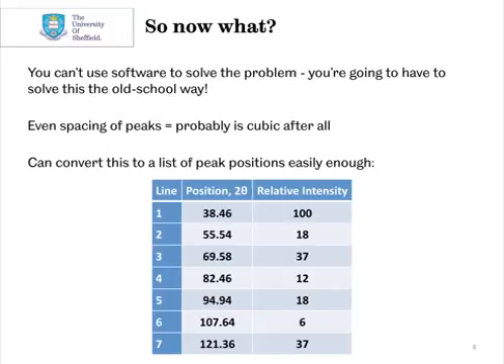From the diffraction pattern, we can see that the peaks are spaced fairly evenly. This indicates that the sample probably does have cubic symmetry after all. So we can create a peak list quite easily. As you can see here in the table, we've got our 7 peaks from the diffraction profile, and we've listed the peak position in theta and the relative intensity. What's important is that as we go through this exercise, you'll notice I don't refer to the relative intensity at all. Everything we're going to do is purely from the peak position.